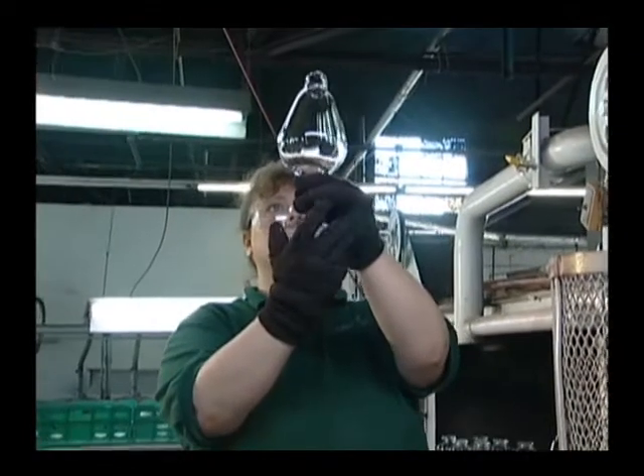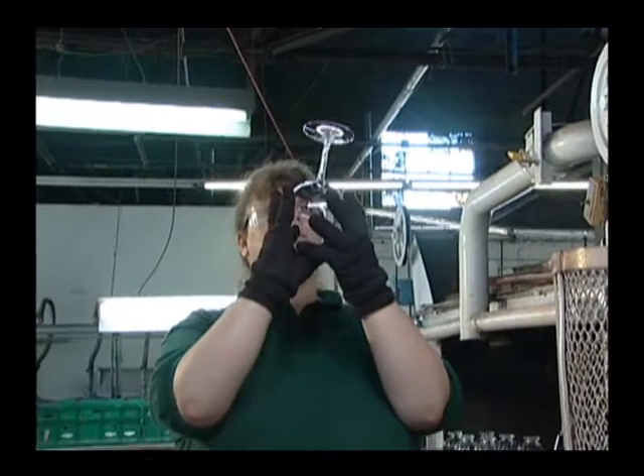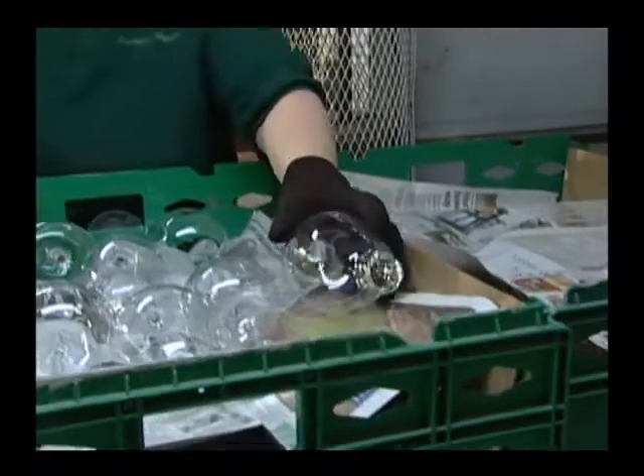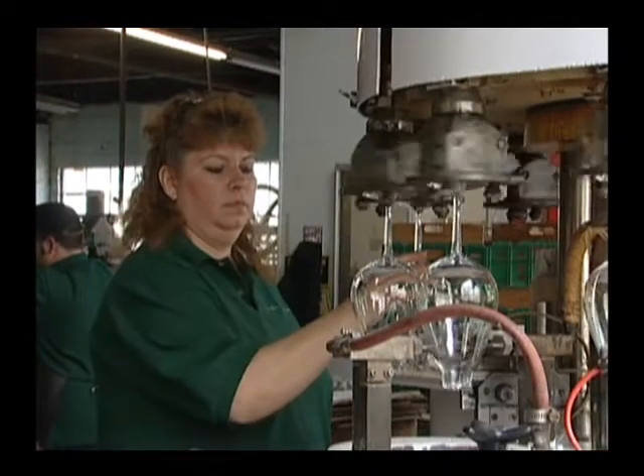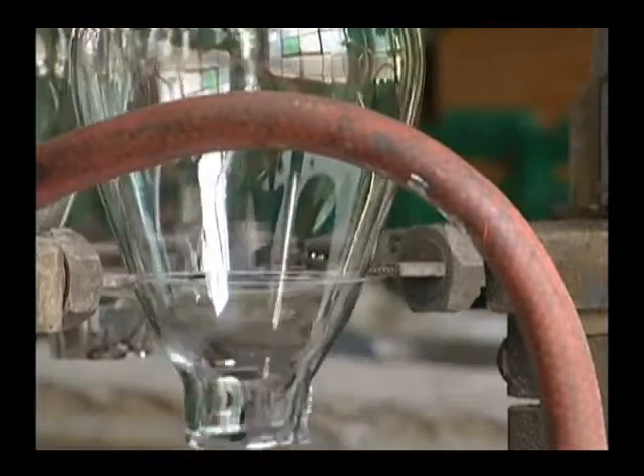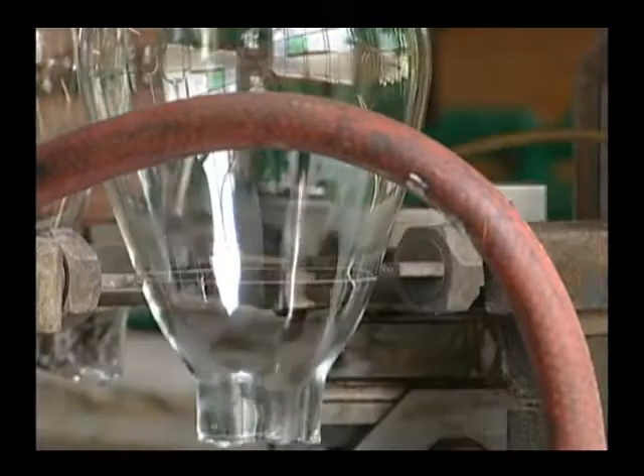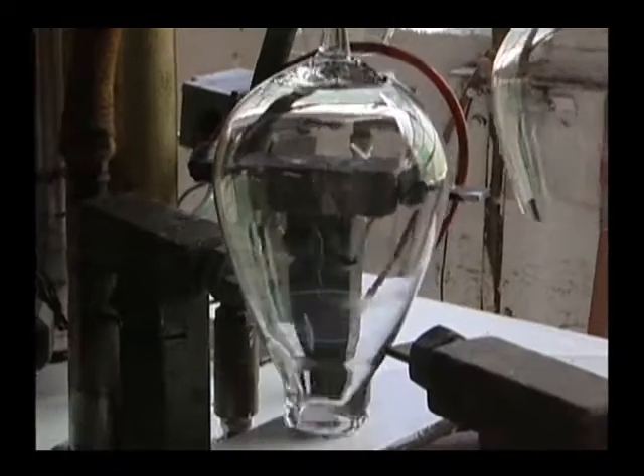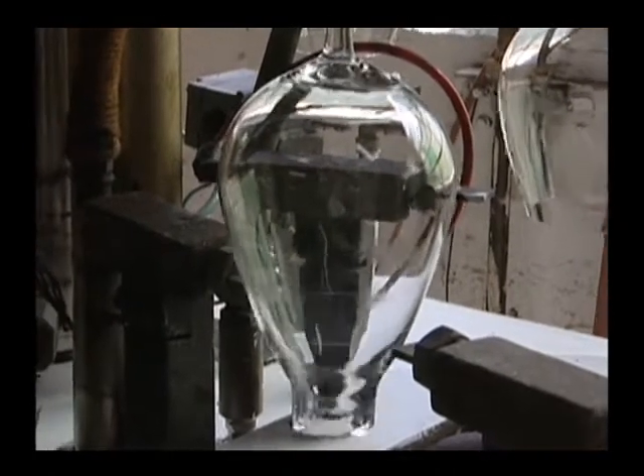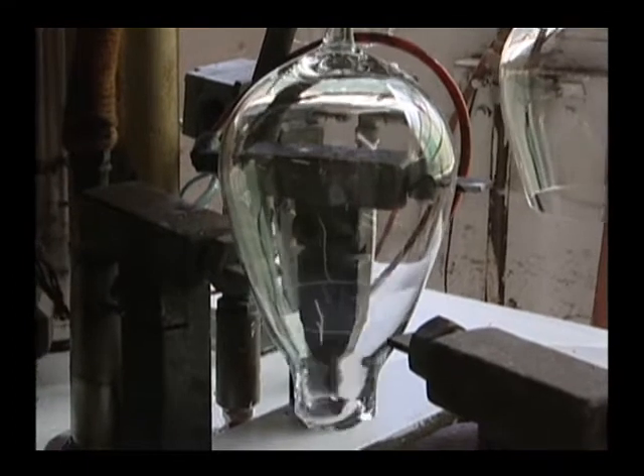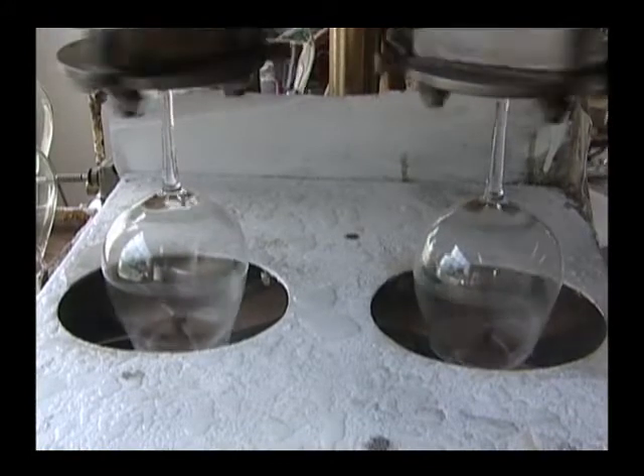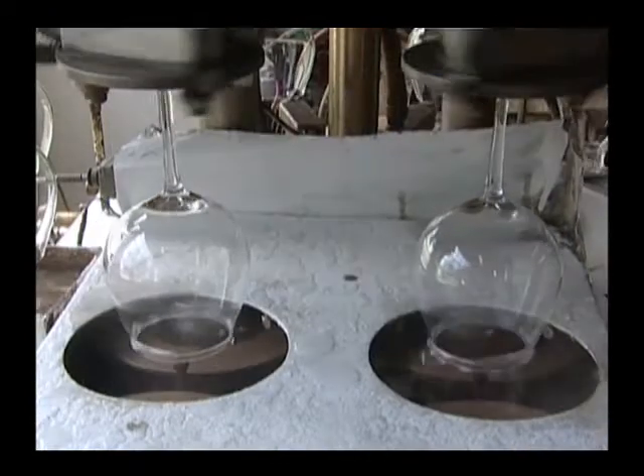If approved, the wine glass is sent to the finishing department, where the overblow or moil at the top of the glass is removed. After being scored with a carbide wheel at the desired crack-off height and then heated with a hydrogen-oxygen flame, the piece is chilled with an air knife. The ensuing temperature shock induces a crack around the score line, which enables the moil to separate from the wine glass. The wine glass is then diamond ground in two different stages.